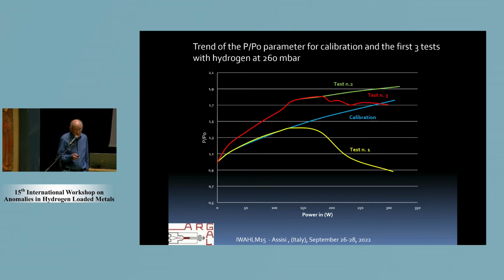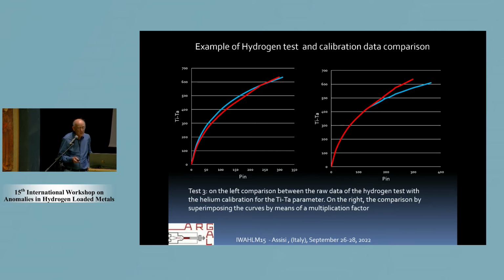This test was one of the best, showing a quite high extra heat. This is exactly the behavior of the temperature during this third test, where I forced a reabsorption of hydrogen from 500 degrees to 700.